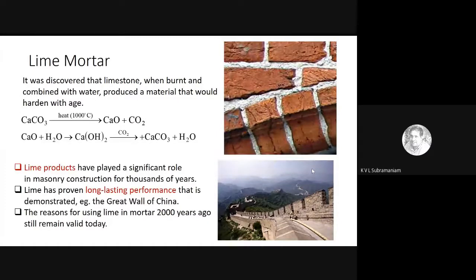It has been traditionally used even in India. Practically everything that was built up to almost 100 years ago was made with lime mortar. And it's a very simple chemistry here, where you take limestone, which is basically calcium carbonate, you heat it to 1000 degrees, essentially calcine it. That breaks up into calcium oxide, which is what we call chunna or lime powder, and you mix it with water. That turns into a paste, and that paste basically is calcium hydroxide.